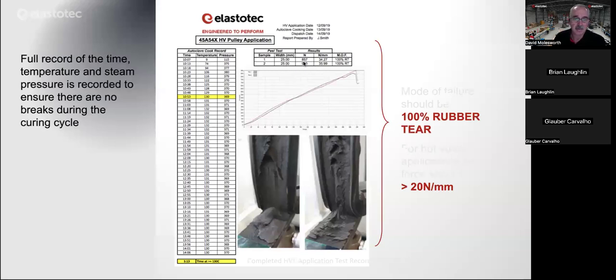Here you get the result at the top. We've got, in this case, 34 and 35 newtons per millimeter, and MOF is mode of failure, 100% rubber tear. So we're basically saying that the failure is just in the rubber. There's no debonding or delamination. The spec that we use for pass-fail criteria is the adhesion should be more than 20 newtons per millimeter, and the failure should always be 100% rubber tear.